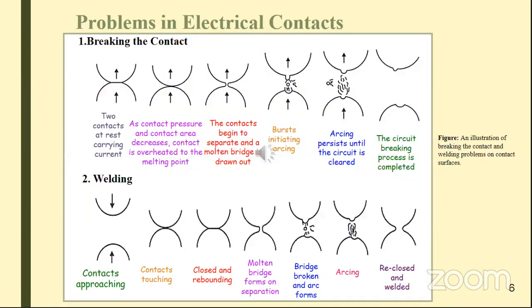And here you can see the damaging of contact surfaces during operation. There are two main reasons for contact failure: breaking the contact and welding. In breaking the contact, as you can see, first two contact buttons carry current. While they are separating, contact pressure and contact area decrease, so the contact is overheated to the melting point. And this causes a molten bridge to occur between the contact surfaces. When this bridge breaks, a burst initiates arcing. The arcing persists until the circuit is cleared and the breaking process occurs.